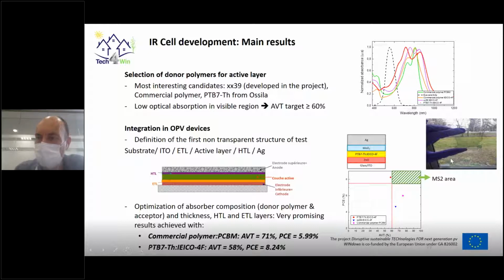Another interesting issue is related to the optical quality. Here you can see a photograph of the absorber layers with the combination of the donor and acceptor polymers deposited on glass. In this case, it corresponds to the commercial polymer with PCBM, and you can see that it's really a high quality layer with almost no color effect, so it's essentially color neutral. So now, at this moment, what we are working on is analyzing the compatibility of these solutions with the industrial requirements, because what we need is a solution that is compatible with the roll-to-roll processes that will be developed at the industrial site.